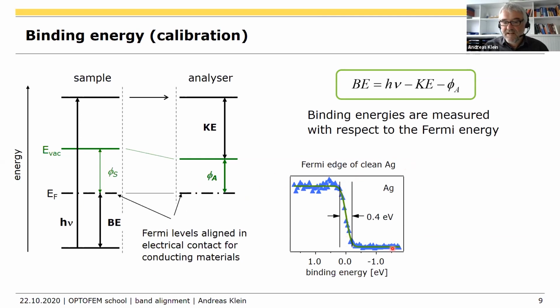That's not only the thermally broadened Fermi edge, which it is, thermally broadened because it's at room temperature, but it's also convoluted with the resolution of the spectrometer system. So by measuring this Fermi edge, we can in principle also determine the spectral resolution of our spectrometer, which is mainly the width of the X-ray source. How good our monochromator is.